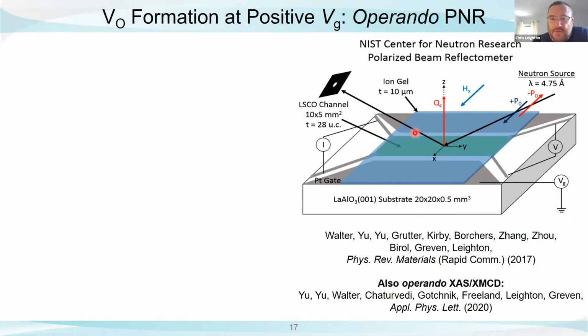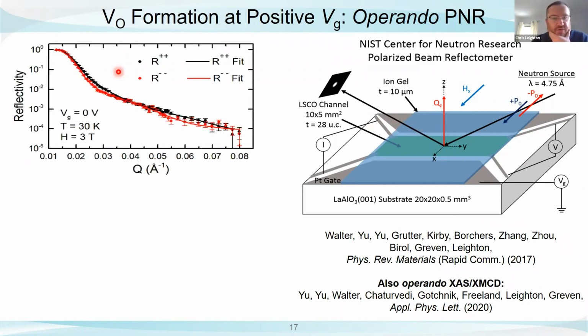We're going to be reflecting neutrons from the surface of our magnetic material. Neutrons, of course, have finite spin, so we can polarize them what we call plus, meaning they're parallel to the magnetization of our material. We can orient them minus, which is anti-parallel to the orientation of our material, and we can analyze their polarization on the way out so that we can plot the neutron reflectivity as a function of scattering vector.